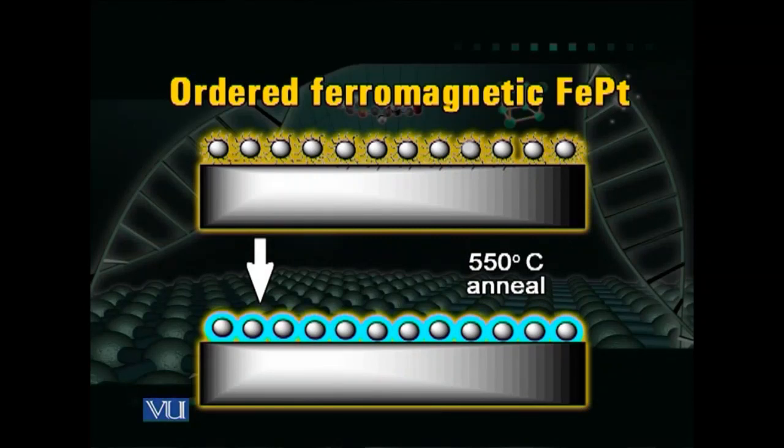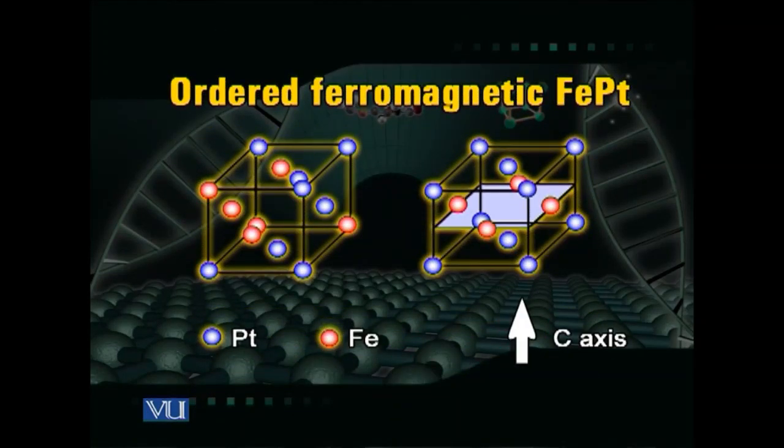the top, and then I can spin those onto a surface. If I do that at room temperature, the structure is not particularly useful because I haven't rearranged the blue and the red atoms into the magnetic state that I want. But if I cook it a little bit, then I do. And now I have a magnetic array that's based on nanoparticles.